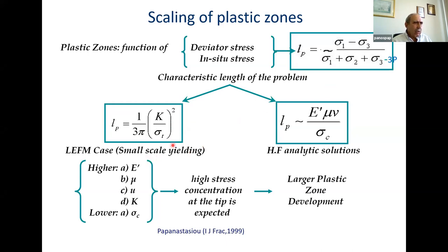It will depend also on the toughness of the material and the tensile strength. This is a question from classical fracture mechanics, but then from the analytic work we did at that time in Schlumberger Cambridge Research and the very famous solution published, we can get this characteristic length, which includes the plane strain modulus, the pumping parameters, and the compressive strength of the rock. So overall, we could say we'll get larger plastic zones if we have high elastic modulus, high pumping rates, high original toughness, and low rock strength. Basically, these parameters change the stress concentration near the tip and create larger plastic zones.